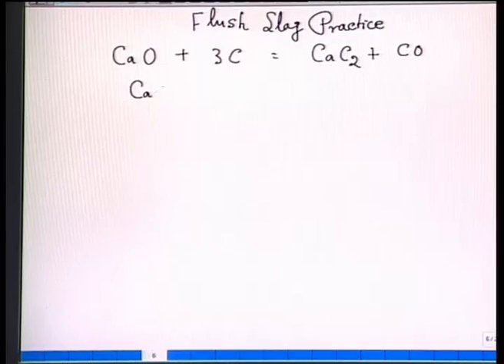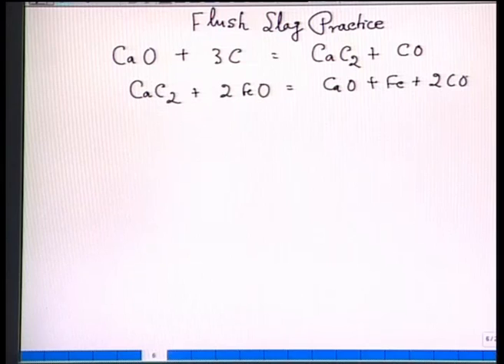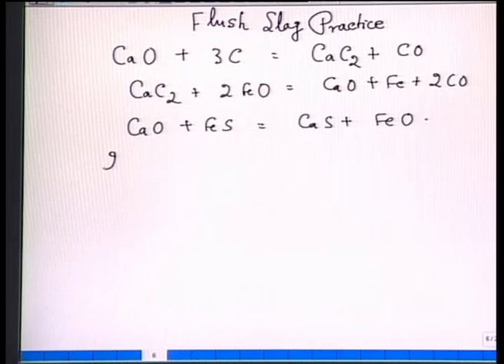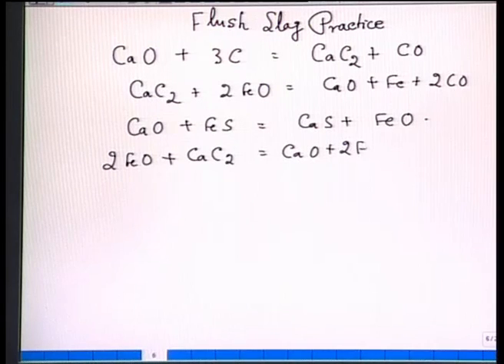Now, this carbide in the slag, it reduces FeO content. That means CaC2 plus 2FeO, that is equal to calcium oxide plus iron plus 2 carbon monoxide. Now, this calcium oxide, which is again being produced, it reacts with FeS and forms CaS plus FeO, and 2FeO plus CaC2, that is equal to CaO plus 2 iron plus 2 carbon monoxide. That is how the process of desulfurization of hot metal in electric arc furnace is being done.